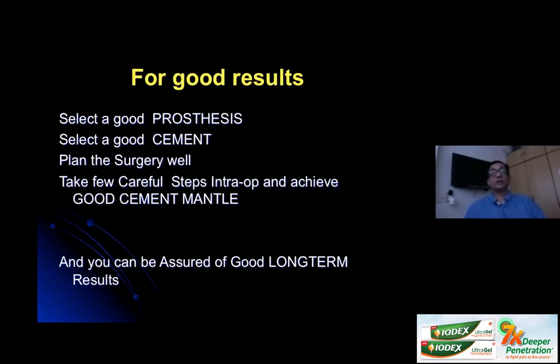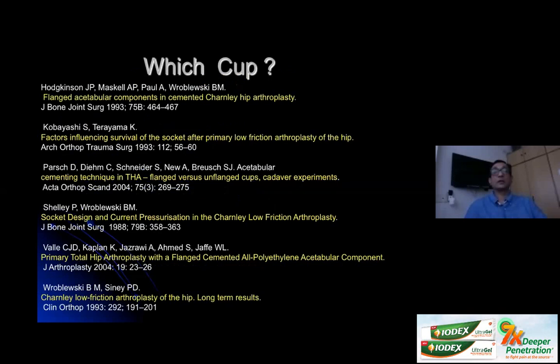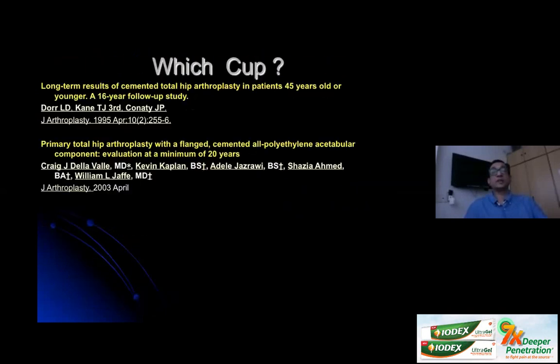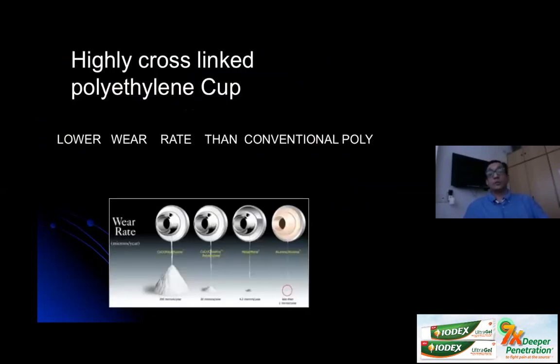So you can conclude that to get a good result in cemented hip, one needs to select a good prosthesis, select a good cement, plan your surgery well, take a few careful intraoperative steps to achieve good cement mantle, and you can be assured of good long-term results. If you go through the literature, which again, there's a huge amount of literature since we've been doing it for the last 60 years, we can easily conclude that the most important thing that leads to failure is the bearing.